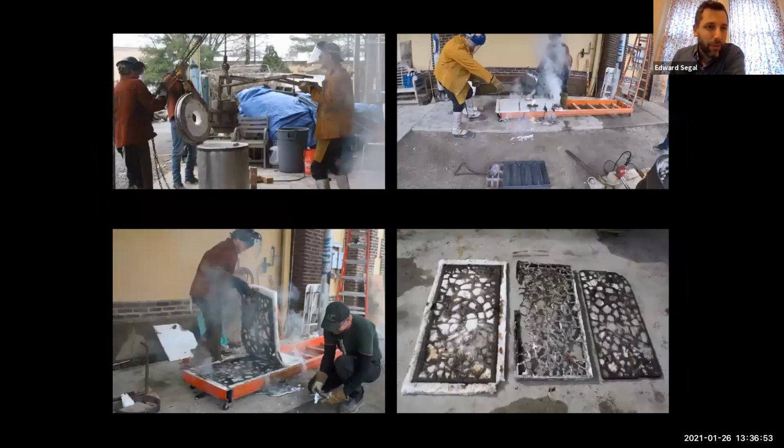Okay, so what's going on? Well, when you dry the clay, you can't get it perfectly dry like you would in a typical casting process when you use resin bonded sand. And so any moisture that's trapped in there is escaping in the form of steam. Now, the reason that you saw the aluminum pour through the bottom was we were using a low-cost wood bottom for the form, and we sprung a leak.